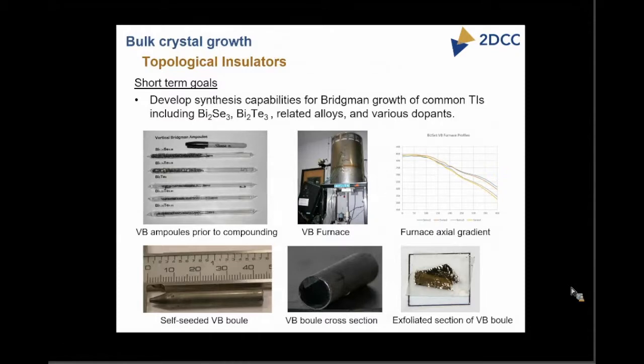The other area that we've started work on, topological insulators, from the short-term perspective, again, using this as a means to stand up the Bridgman capability for these materials, starting with bismuth selenide, bismuth telluride related alloys, and dopants. A couple of figures here to show this work. These are examples of different vertical Bridgman ampules that were prepared with different selenium concentrations for bismuth selenide, bismuth telluride.